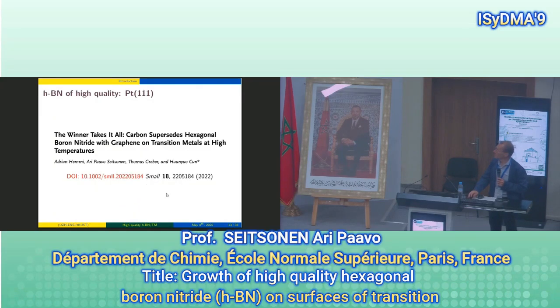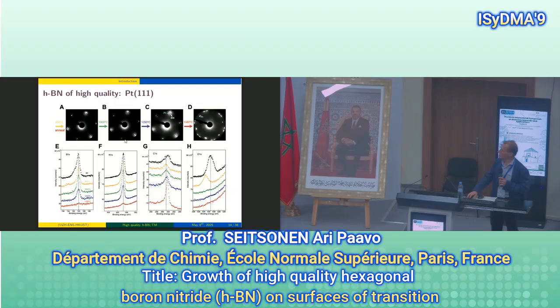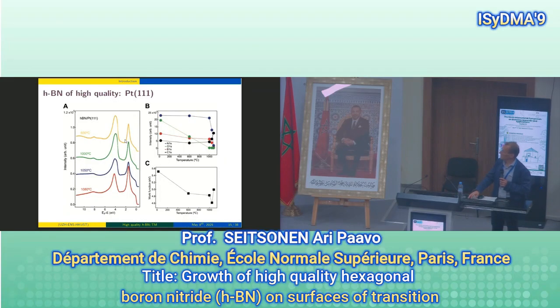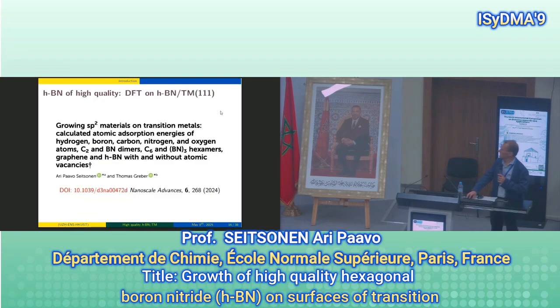So that was the title, The Winner Takes It All. If you just heat it, maybe you get something different than you were hoping for. And here it's carbon, because the carbon binds strongest on the platinum-111. This shows the same effects again, seen in the UPS and in the intensity of the XPS, but this is what we already saw. So the intensity of carbon just goes up with annealing temperature. Those are the red, the black dots. So the intensity goes up with the annealing temperature.